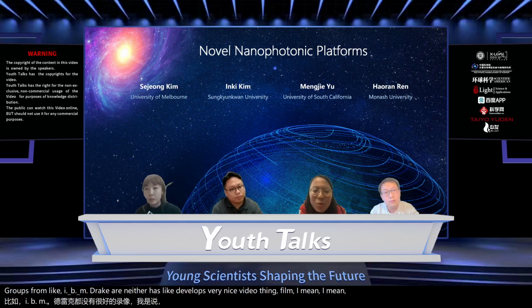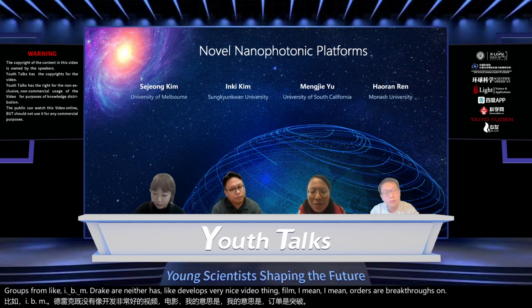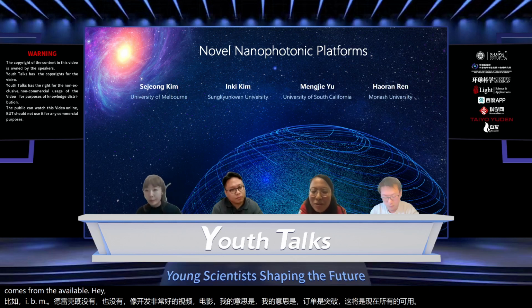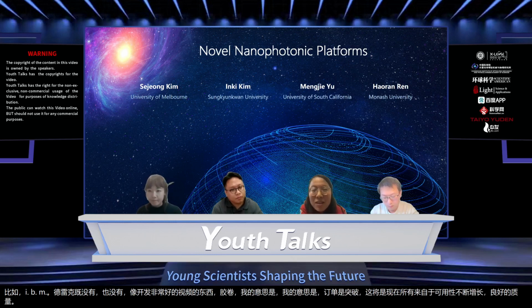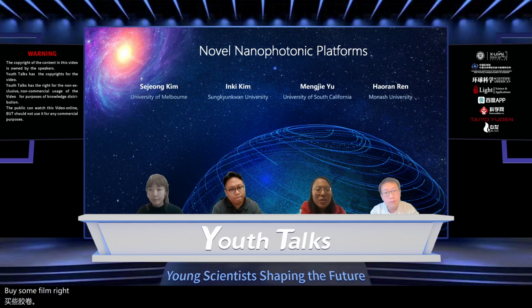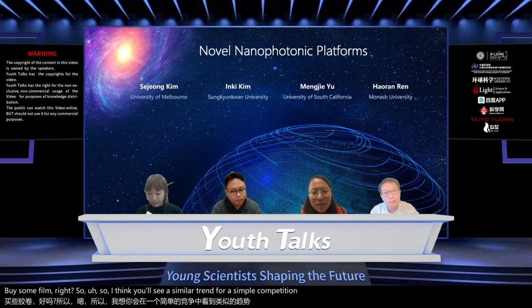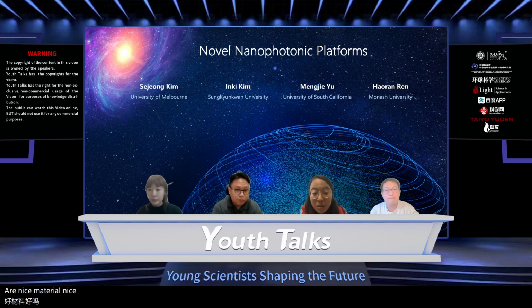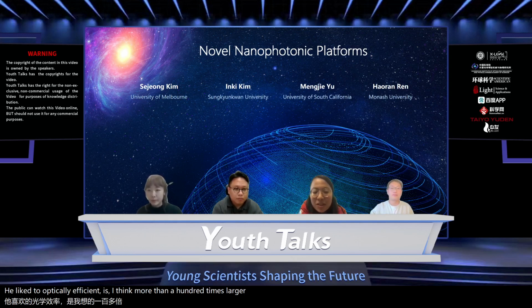All these breakthroughs on lithium niobate come from the availability of growing good quality thin film, right? So I think we'll see a similar trend for thin film BTO as well. BTO is a very nice electro-optic material, and its electro-optic coefficient is, I think, more than 100 times larger than lithium niobate.